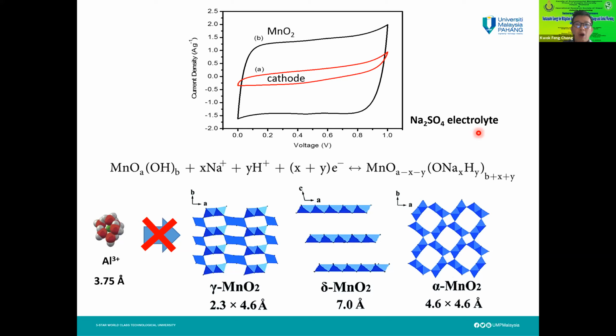It doesn't fulfill the objective of our initial test, whereby we want to see whether aluminum ion can be inserted into the manganese oxide. Then we do the study. The aluminum hydrated ion has an ionic radius of 3.75 angstrom. But if you look at those different morphologies and crystal phases of this manganese oxide, practically it should be able to accommodate this small radius of aluminum 3+. Experimentally, we couldn't see any aluminum 3+ inserted into the voids of this manganese oxide.